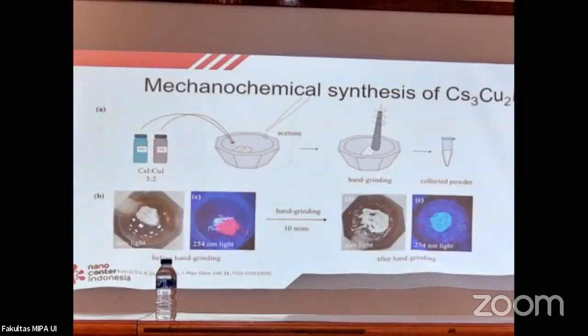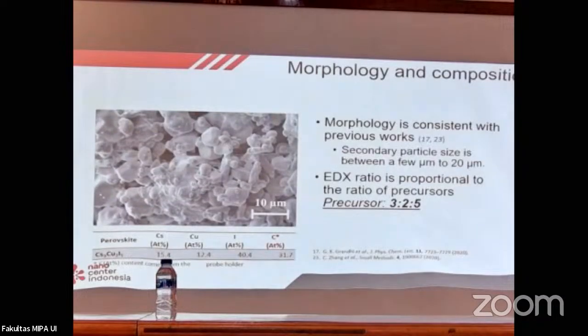So this is the synthesis. You pour in two precursors, and then after introducing a small amount of acetone, you just use a hand grinding method. In Indonesia we call it ngulek. And then after you gain enough good homogeneity in the sample, as shown here by Toby, the before and after, you check whether you managed to get the targeted perovskite by illuminating it with UV light. You will see two astonishing features in which you emit a blue emission for the copper after being irradiated with 254 nanometer. So this is how the morphology looks like.